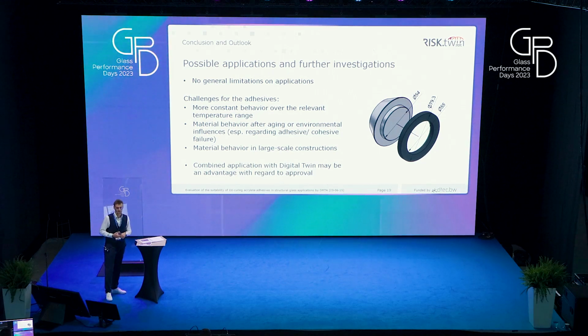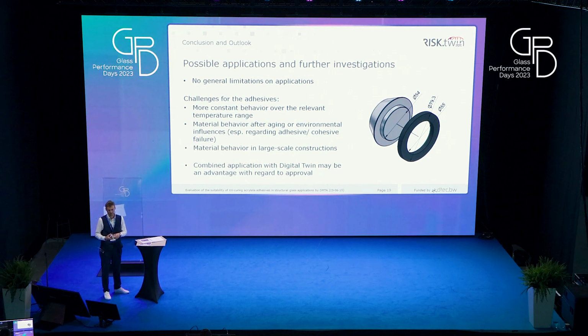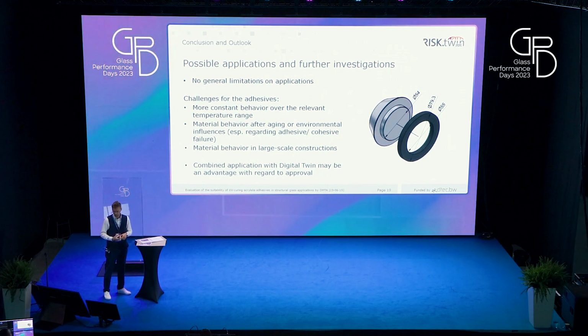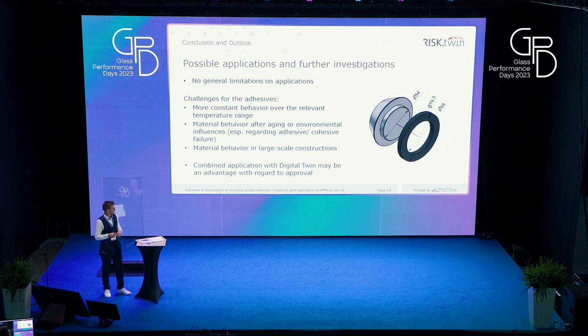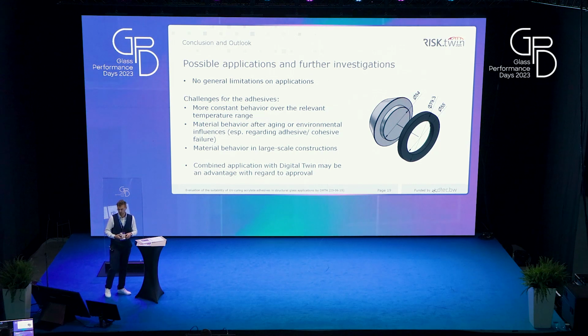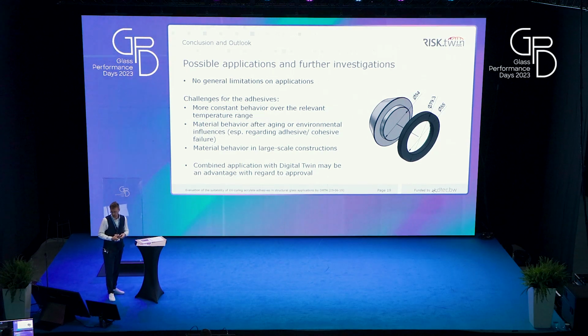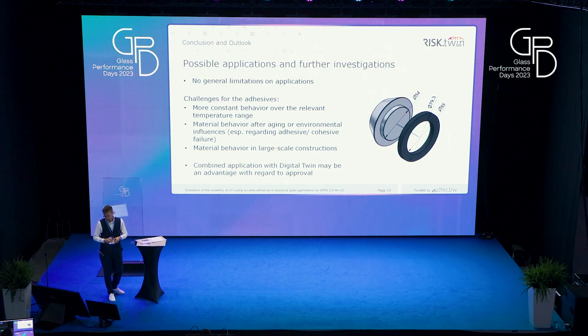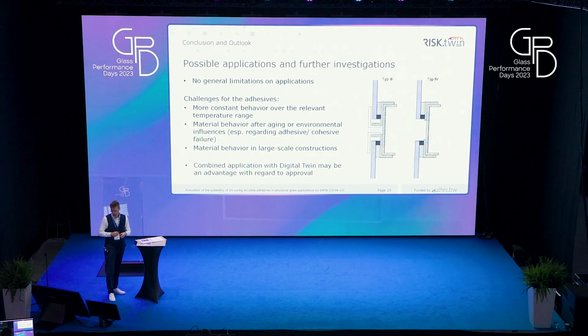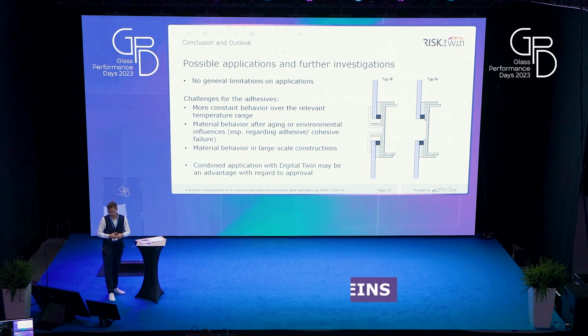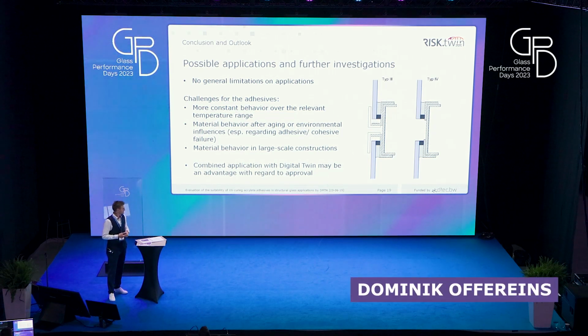So in this point fixing, we want to apply adhesives with 2 different stiffnesses to obtain a redundant behavior. So the adhesive in the center of the point fixing should be a very stiff one, which is actually responsible for the load transfer. And the one in the circular ring around the other adhesive should be softer to be able to carry some load in case that the stiff adhesive fails for whatever reason, which is not expected. And with that, why not go for other connections like linear bondings, for example, the type 3 and type 4 of the ETAG 002.